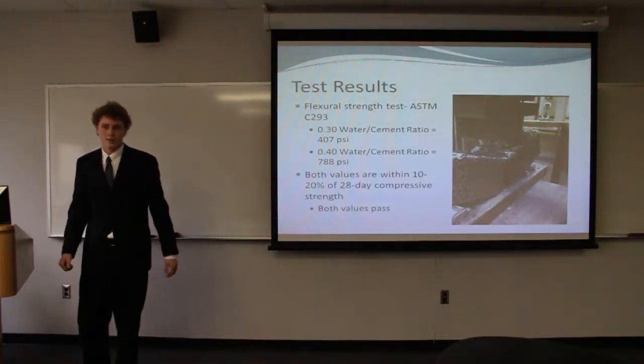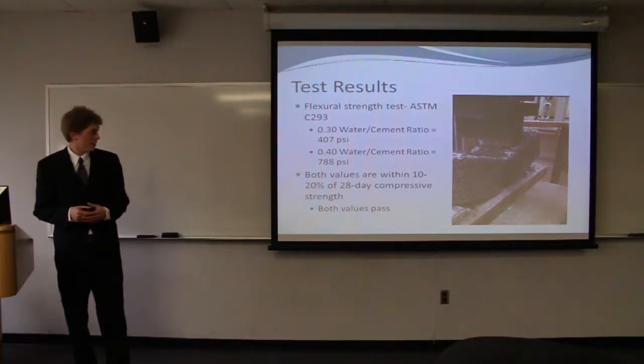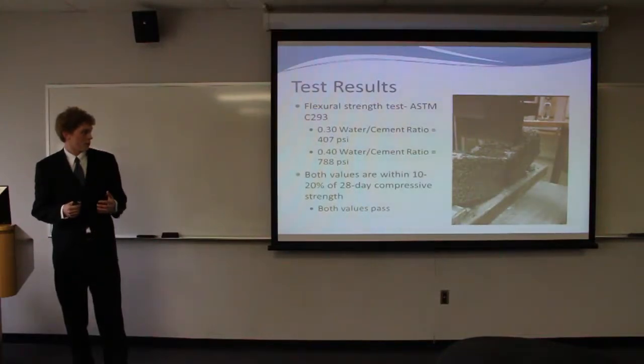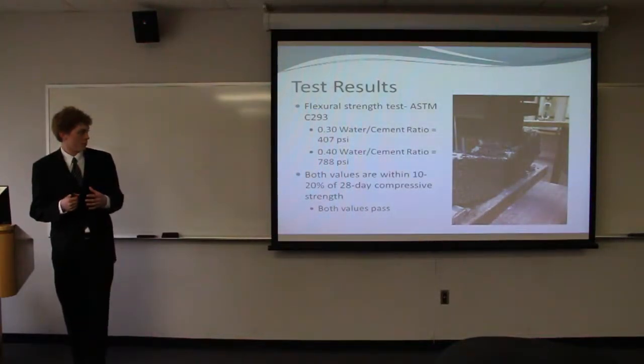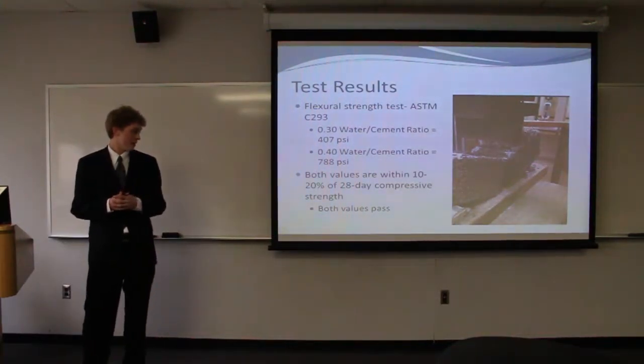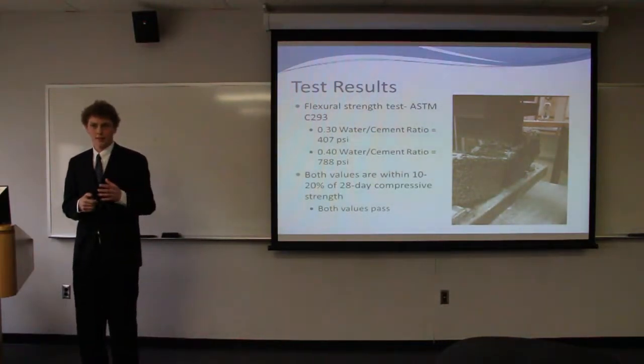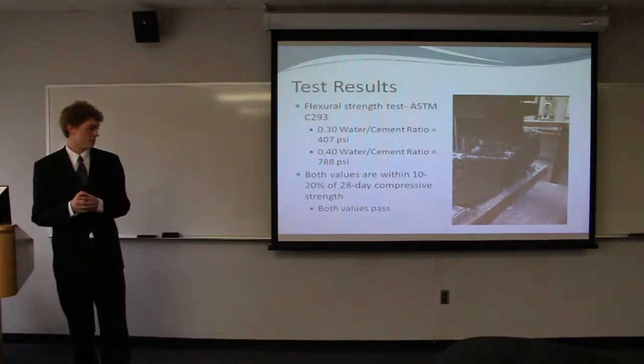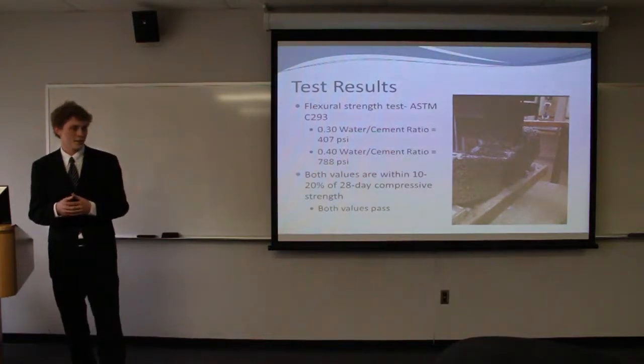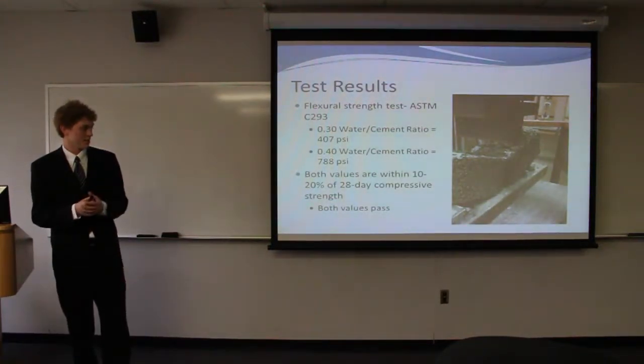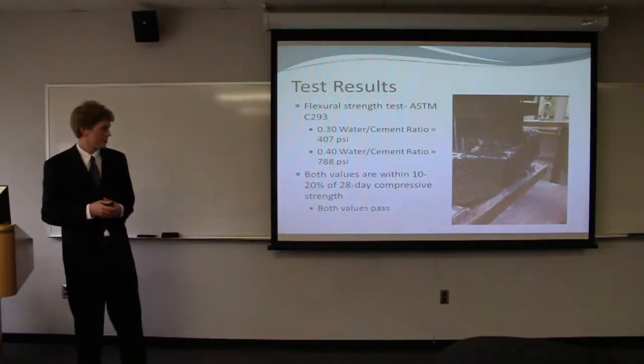We also performed a flexural strength test on the pervious concrete. The .30 had a 407 psi, and the .40 had a 788 psi. Both of these values are within 10 to 20% of the compressive strength, so both of these values pass the test. And to the right, again, it's just us doing the flexural strength test.